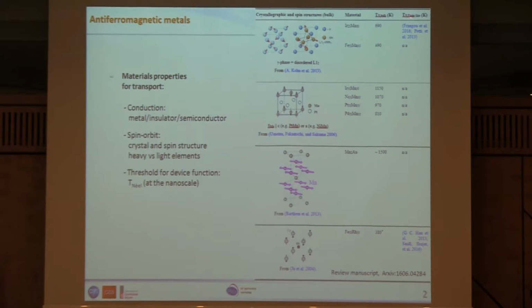Now I also want to focus on these two last columns, because at the end of the day, if you want to have a ferromagnet-free memory, the temperature threshold for the device function is the Néel temperature, which is the temperature for the magnetic phase transition between antiferromagnet and paramagnet. Hopefully there are some materials that have a bulk Néel temperature above room temperature. But if you want to work with nano devices or with nanometric samples, what counts is not the bulk Néel temperature, which is pretty well known for most materials, but the Néel temperature at finite sizes.